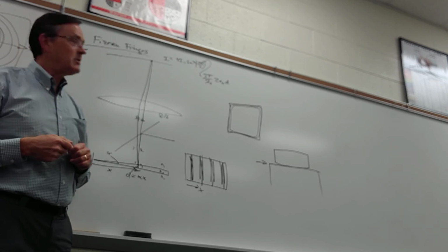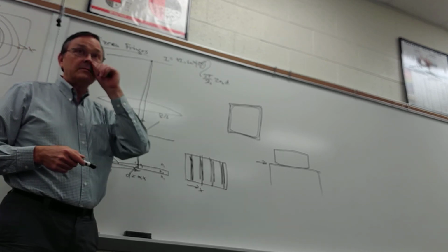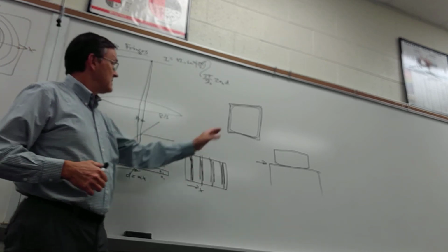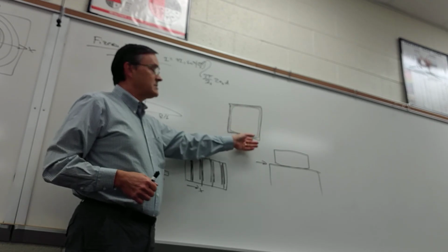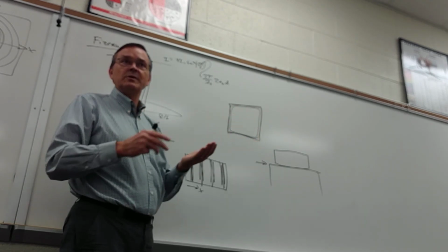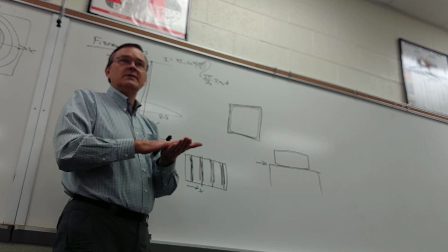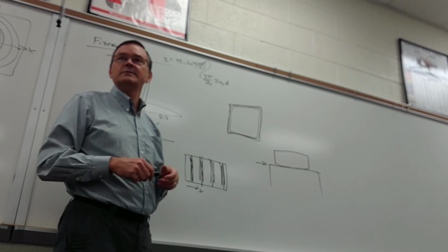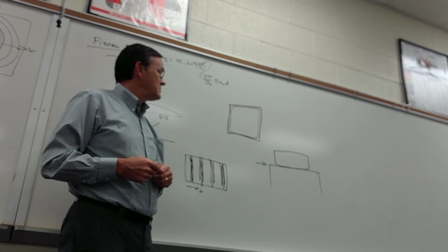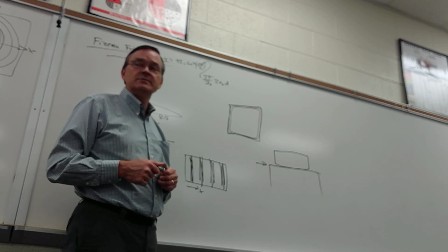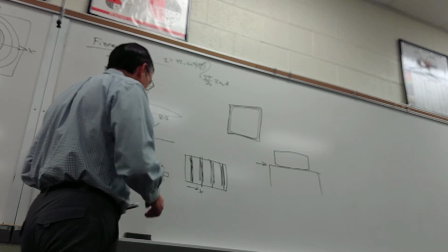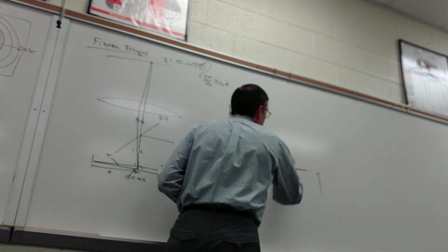And what would it mean if you have fringes like that? It's pretty flat in the middle and it curves a little bit on the edges, which is typical with polishing. When you're polishing, the edges tend to get rounded just a little bit. So he would use this method all the time to figure out how good a polishing job he'd done.